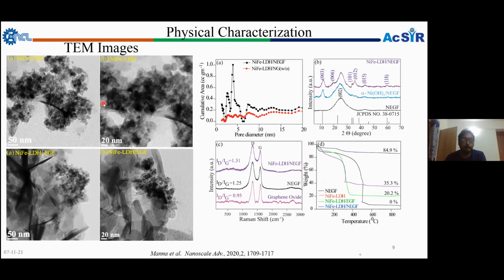So as we have studied thoroughly for the without support and without nitrogen, as we already told, in the presence of nitrogen there is a contribution, because nanoparticles are growing in the presence of nitrogen, which changes the electronic environment of the graphene substrate, the carbon substrate. When nitrogen is doped over that, the electronic distribution changes completely.